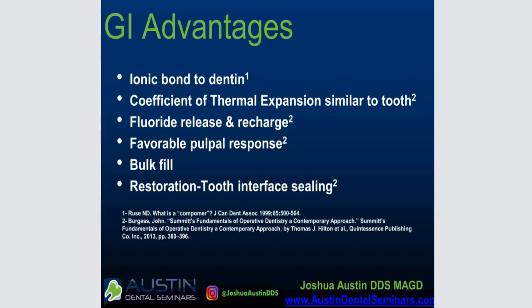We think about favorable pulpal response, and when you put a glass ionomer in, there's kind of an initial period of it being pretty acidic, and that can actually be somewhat irritating to a pulp. But that acidity balances out really quickly, usually within 24 hours, and reaches a really nice threshold within a day of placement of the restoration and setting of the material. And typically speaking, we see less pulpal irritation and inflammation around glass ionomers than we do other types of materials, resin composites specifically. Glass ionomer is not going to be great to be used as a direct pulp capping material, but when you talk about an indirect pulp cap, glass ionomer type of restorative materials work really, really well.